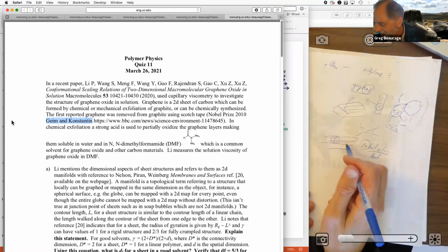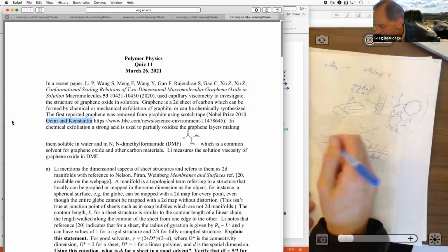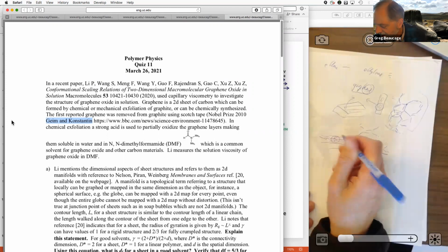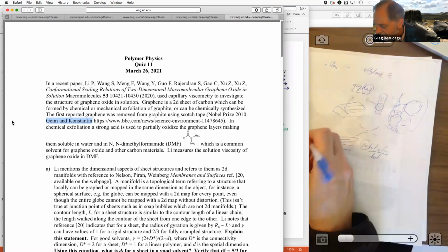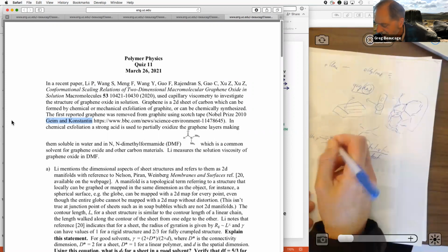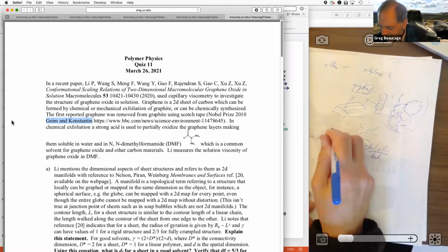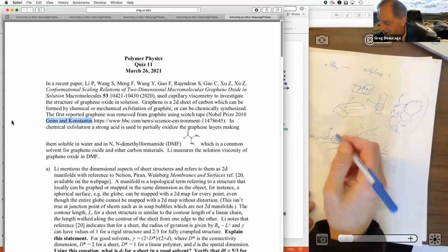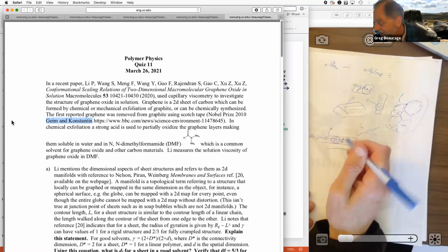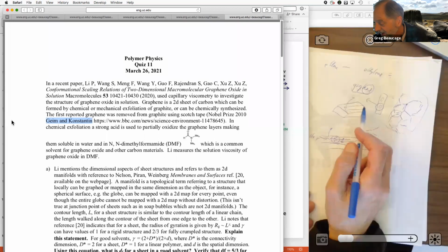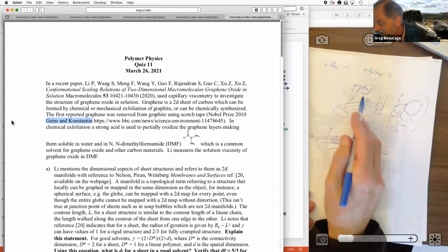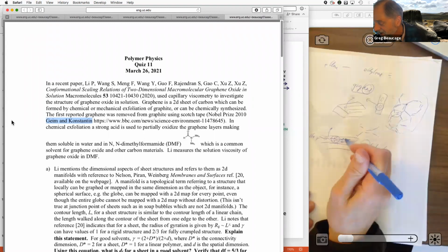So you'd come in with chemicals, particularly polymers, that can weasel their way into this gallery, they call it, between the layers. And if it's a charged polyelectrolyte, it can separate these and then you can exfoliate a clay that way, ending up with single layers of clay. With graphene, they use the same thing, except this isn't a charged structure. So clay is a charged structure, graphene isn't.